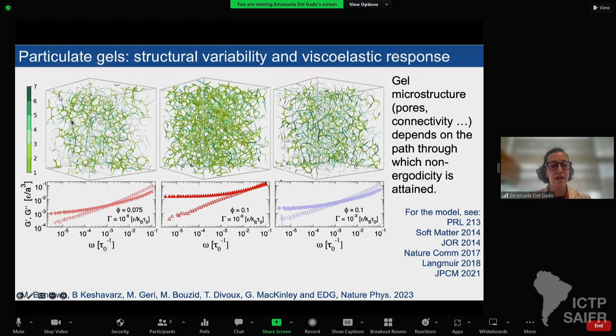So in the simulations I'm producing these types of structures through a process that mimics as closely as possible what would happen in a typical experimental system. And then I can perform numerical simulations in which I mimic rheological linear viscoelastic tests, where I'm wiggling the material back and forth to obtain the whole viscoelastic spectrum. What you see plotted beneath the snapshots are viscoelastic spectra, so G prime and G double prime, the storage and loss components of the modulus of the material, as a function of the frequency when we vary these frequencies over a broad range in the simulations.